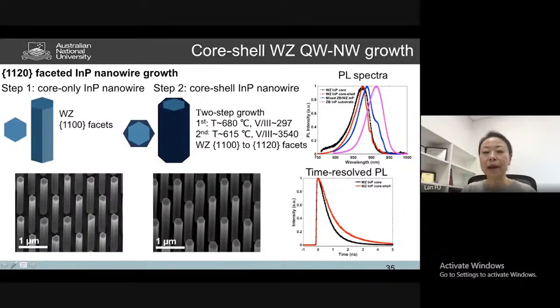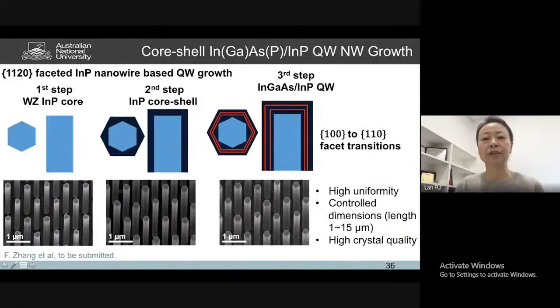But by doing that, remember we said that when we adopt this low temperature recipe, we actually rotate the facet. You can see the rotation of the facet here as well as here, right? So when we rotate the facet, the energy of the facet becomes favorable to the formation of zinc blende indium gallium arsenide. So that's a very important, again, crystal facet engineering for our nanowire growth. This just shows that when we do this recipe, we can still grow very good quality nanowires with this core-shell structure and good rotated facets.